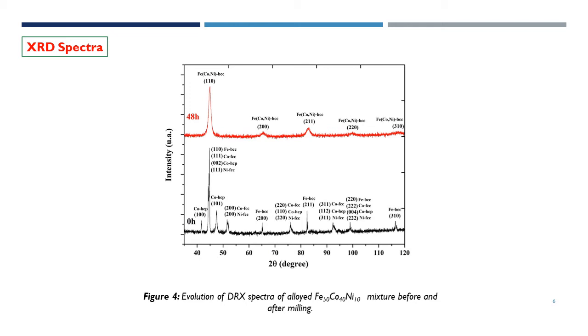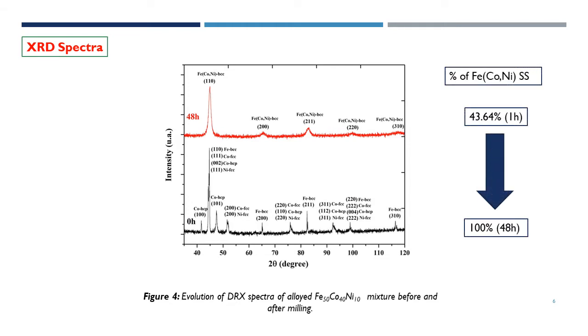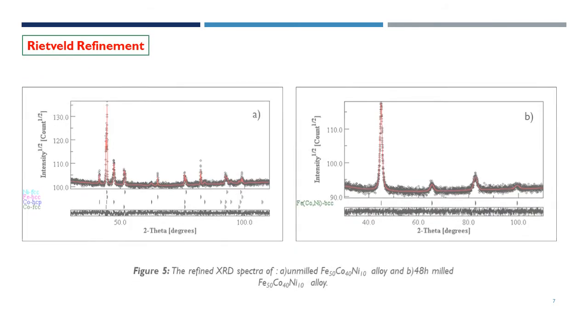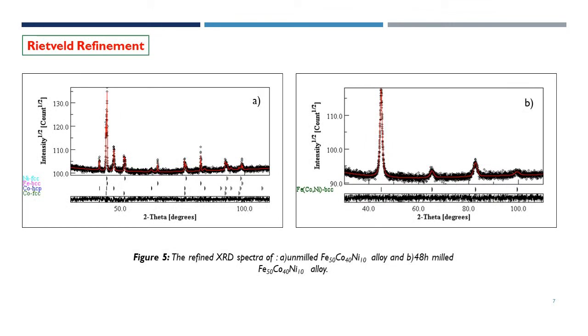The proportion of the new phase solid solution increases from 43.64% after 1 hour of milling to 100% after 48 hours of milling, becoming the only and the total phase existing. Here we can see the typical refined X-ray diffraction pattern of the mixture Fe50Co40Ni10,